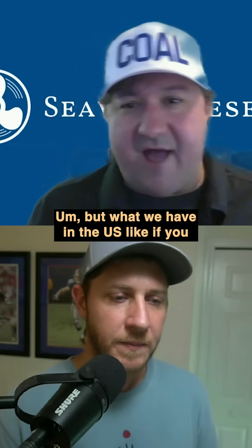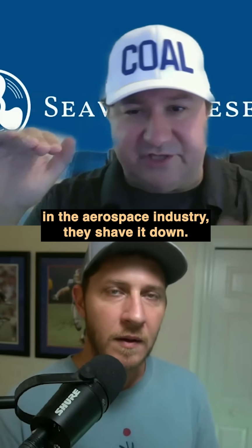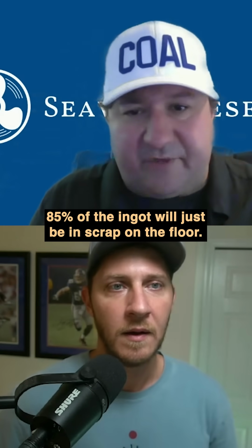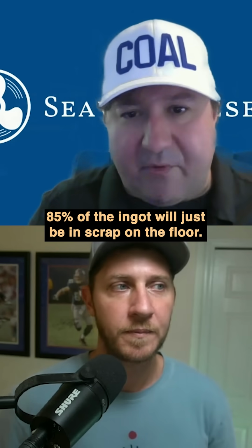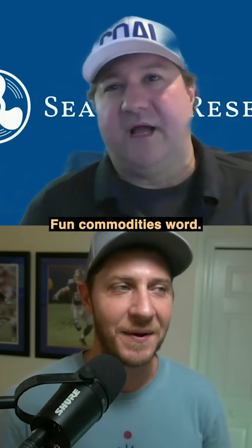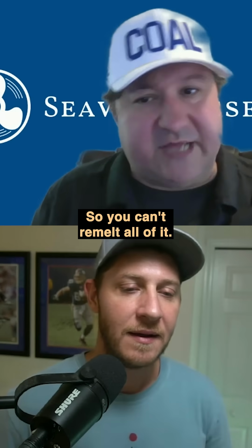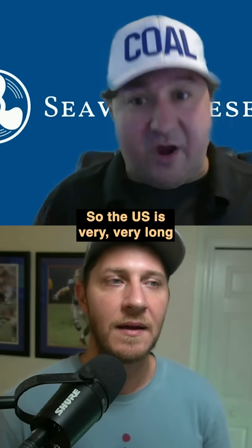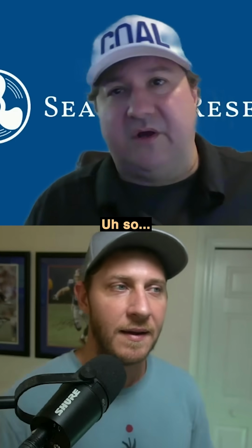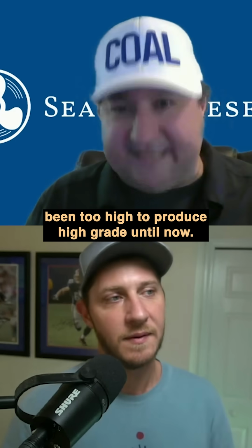But what we have in the U.S., we start with a titanium ingot, and then in the aerospace industry they shave it down, and those shavings, like 85% of the ingot, will just be scrap on the floor. That's called swarf, fun commodities word. They collect all that, and the problem is it gets oxidized when you do that, so you can't remelt all of it. So the U.S. is very, very long all of this titanium scrap. The O2 concentration in the oxidized portion has been too high to produce high grade until now.